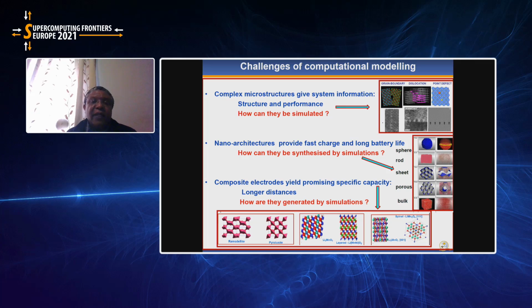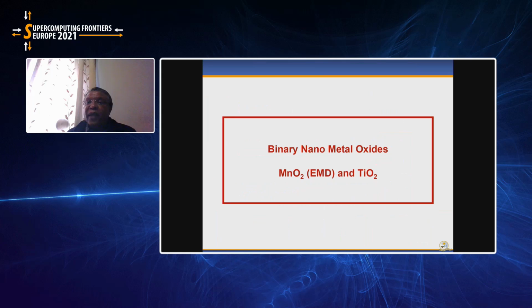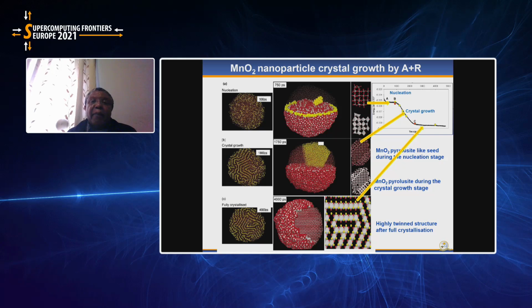And in some instances, we found composite electrodes consisting of polymorphs of the same compound manganese dioxide, for example, having what we call the ramsdellite structure and the pyrolusite structure. How one can simulate this in a spontaneous way is quite a challenge. Now, I'm going to show you two examples of manganese dioxide and titanium dioxide, which are simulated by a technique